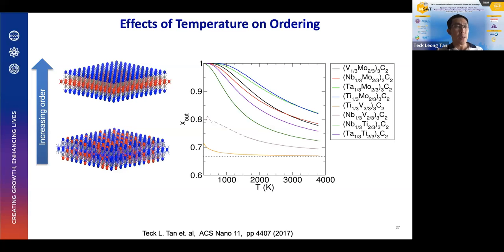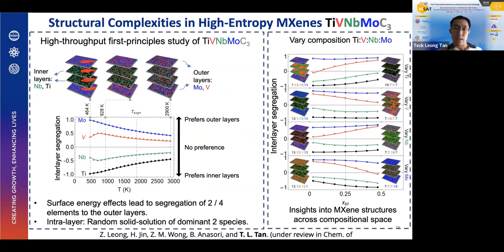So if you're looking at materials design, at alloy design, there are different ways to mix and match different elements, and this will give you different atomic arrangements, which will affect your properties. We also apply it to the study of high entropy MXenes. Interestingly, we see that the disordering is mixed with what we call interlayer separation. Here we study the distribution of titanium, vanadium, niobium, and molybdenum. You can see that in these high entropy MXenes, even at high temperature, there's already some separation between two of the elements. Molybdenum and vanadium like to be on the outer surface, and niobium and titanium like to be in the inner layer.